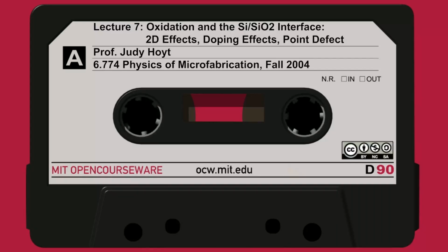After 10, 20, 30, 40, 50, all the way down to 60 minutes, these are all at the same magnification. These stacking faults, these crystal defects, have actually grown quite a bit at 1200 degrees. This is during high temperature oxidation at the surface. These were down in the bulk. So people believe that oxidation was injecting interstitials and causing these defects to grow.